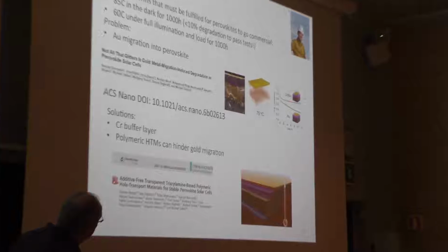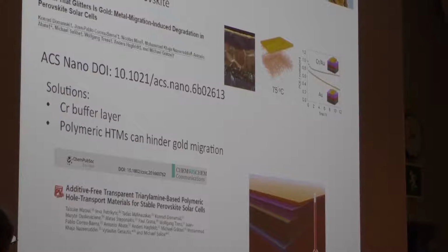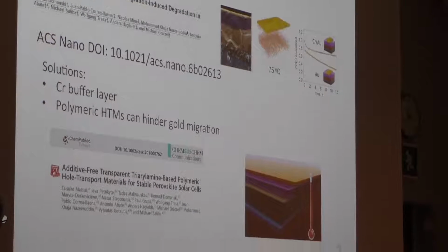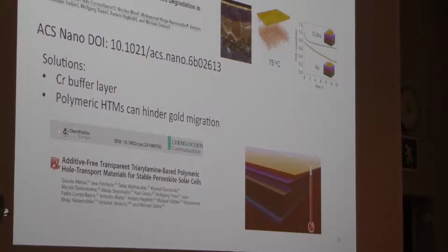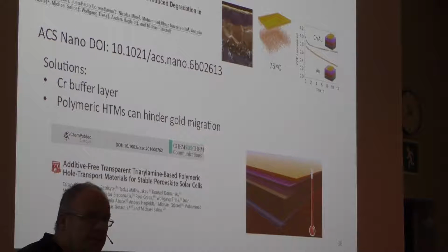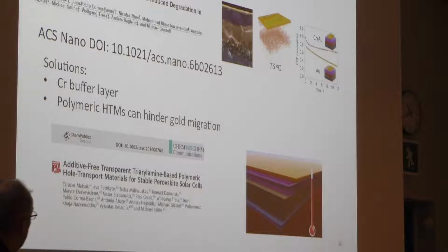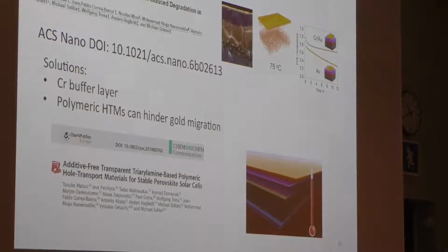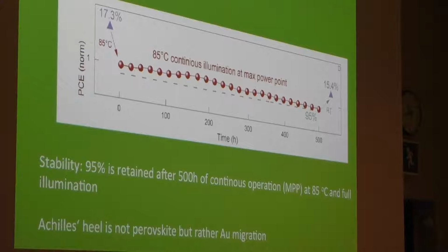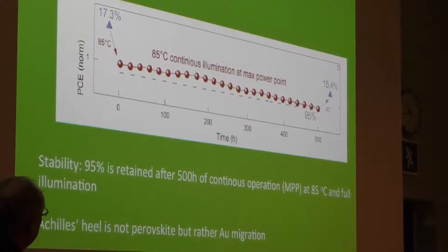One thing we did was to bring a very thin layer of chromium between gold and Spiro, and then you see this improved the stability. This is with chromium, without. You can also say, okay, let's not use Spiro anymore, use a polymer as a hole conductor, which maybe is a barrier to gold diffusion. So that's what we did in this work here, and this is our latest stability data.